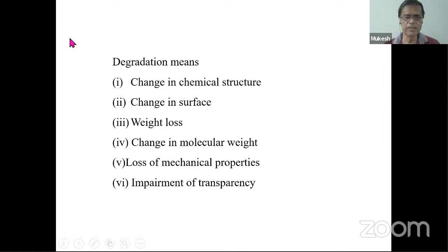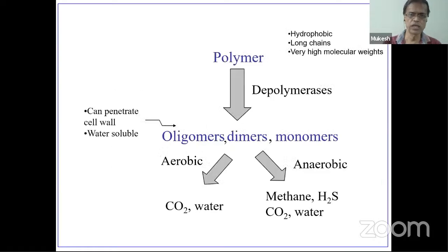Okay, degradation means change in chemical structure, change in the surface, weight loss, change in molecular weight, loss of mechanical properties, impairment of transparency, and so on actually. So generally what we do is we monitor the weight loss, because that's a very clear indication that a material is disappearing. Not just disappearing from the eyesight, but actually getting consumed. That's the weight loss actually.